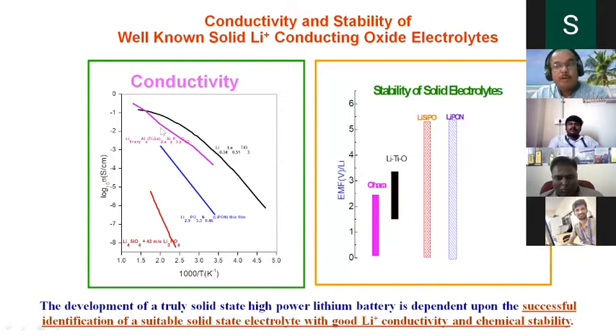But we know very well that we are not only working on the conductivity. If we have the conductivity, then we have to think about stability against metallic lithium. Here, if you see stability, the Lipon has 5.5 volts. So you can imagine making a battery with a 5.5 volt large potential window. Lisipo also the same. But unfortunately, the conductivity is very poor for Lisipo and Lipon.